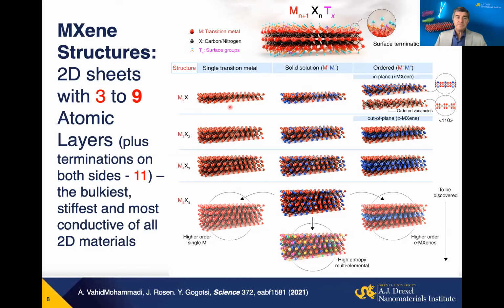Moreover, we can make not only pure material, we can make solid solutions where either M elements or X elements are mixed in a random way. And very recently, the papers were published officially after our Science review, within the last couple of weeks. High-entropy multi-element MXenes, with 4 equally mixed elements, have been reported as well. The story doesn't end here.